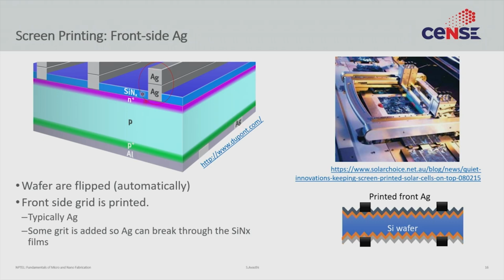Why? Because this Ag paste must penetrate the silicon nitride to make contact with silicon. If you remember the lectures on diffusion, silicon nitride is a pretty good diffusion barrier. It's a masking layer. So you have to do something special to force the metal through the silicon nitride. And what they do is they add some grit, and through that grit, the Ag paste is able to break through the silicon nitride and make contact with silicon. And by using this grit and breaking through, you once again avoid a photolithography step. You don't need to do any patterning. You just pattern the metal using screen printing and do the firing. And during the firing, the Ag will go through the silicon nitride and make contact with silicon. You don't have to do any patterning on the silicon nitride separately, right? So you save a step.